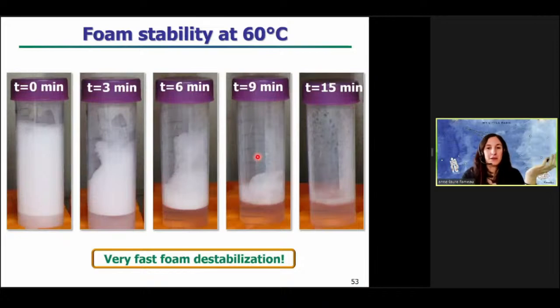Then we wanted to see what is happening at 60 degrees because the tubes turn into micelles at 60 degrees. So we just produce the foam, put the foam in an oven at 60 degrees. And as you can see, we observe very fast foam destabilization. In a few minutes, we don't have any more foams. So the spherical micelles can't stabilize the foam.